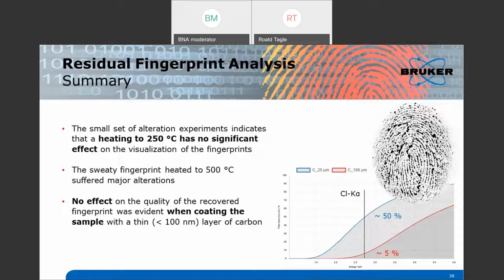And here on the right side, you have a graph of how much chlorine signal you could detect through different thicknesses of pure carbon covering the sample. If you have 25 micrometers of carbon, which is a thick plastic foil, you should still be seeing 50% of the chlorine intensity. If you have 100 micrometers of carbon, which is a lot of carbon, you could still detect 5% of the original intensity. So even under very thick layers of, for example, soot, you should be able to detect the chlorine. And in some fingerprints where you have potassium or calcium, you can even go through thicker layers of this carbon.